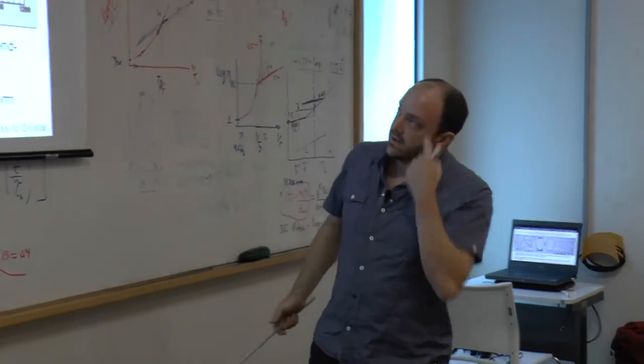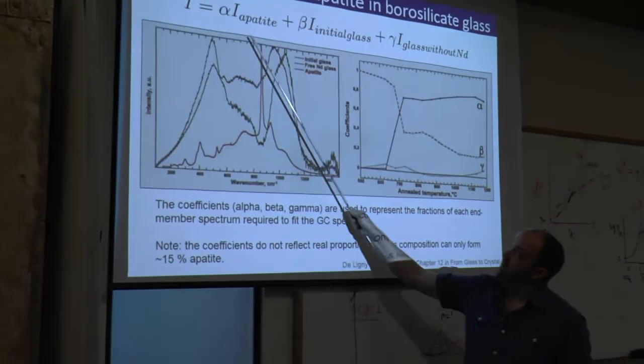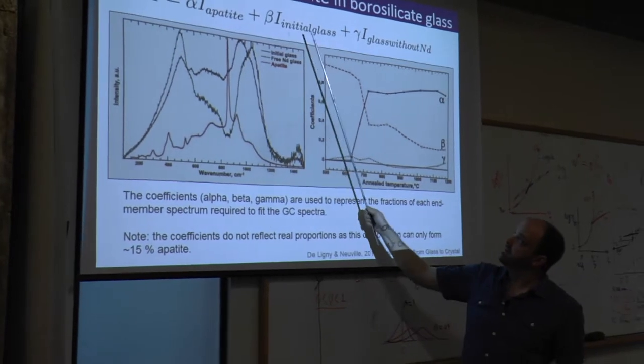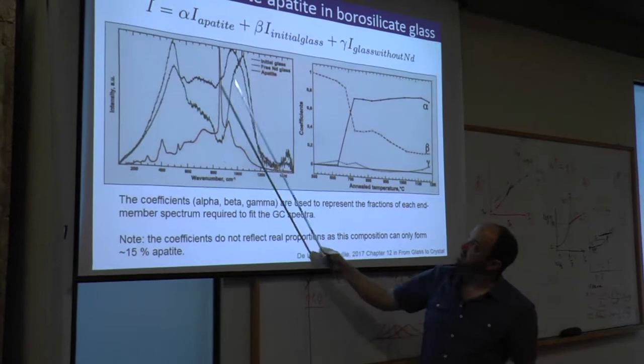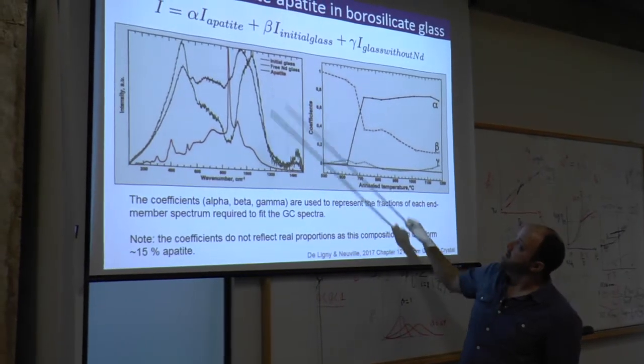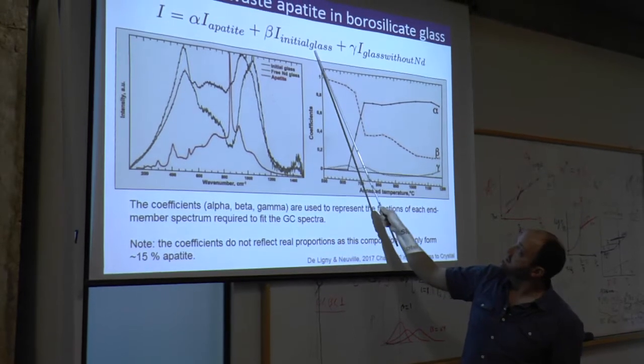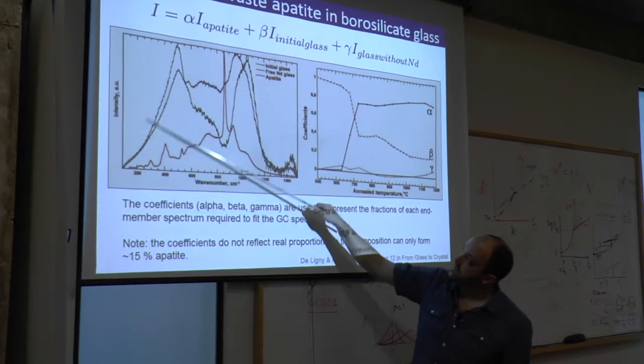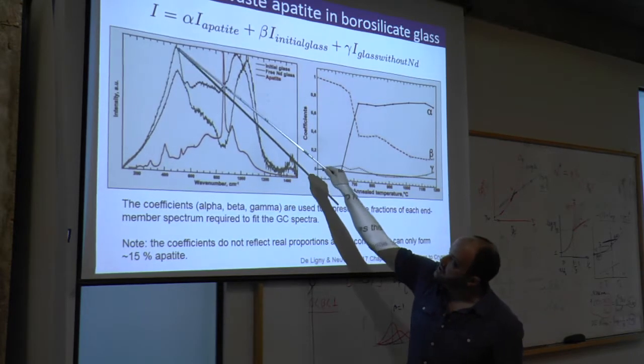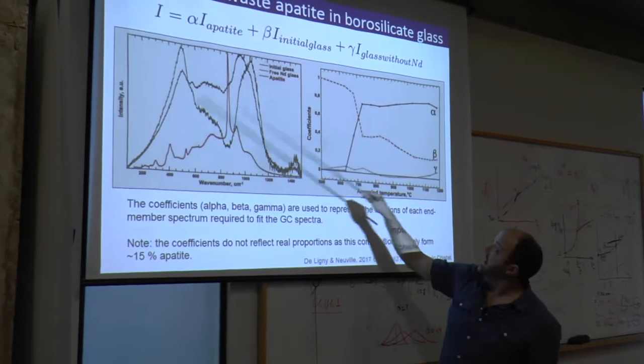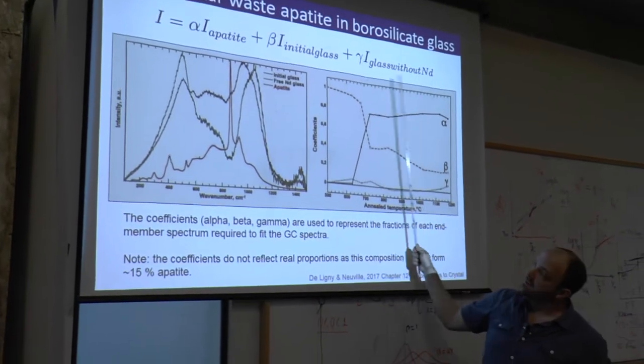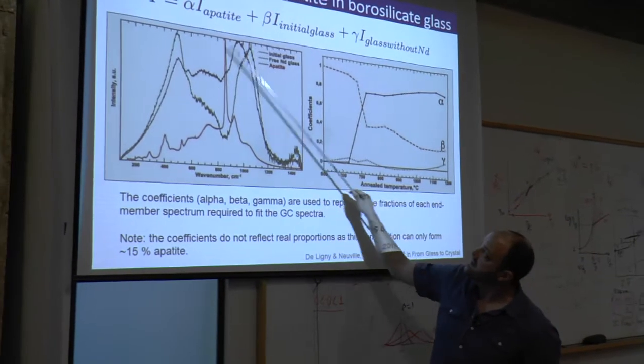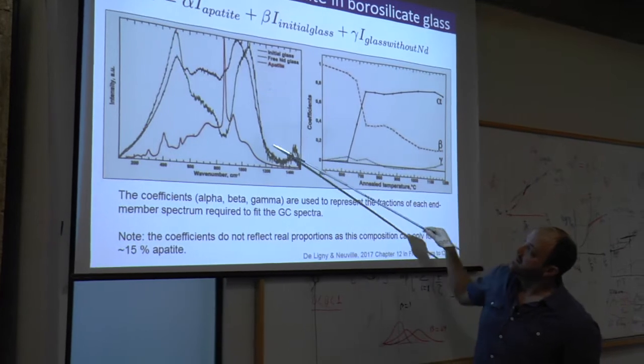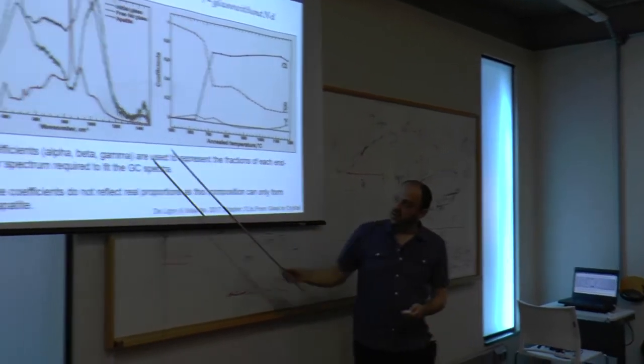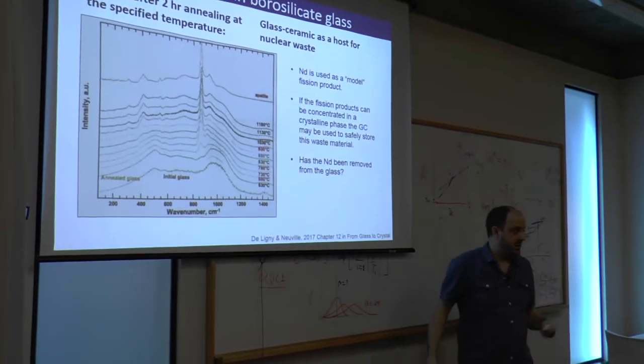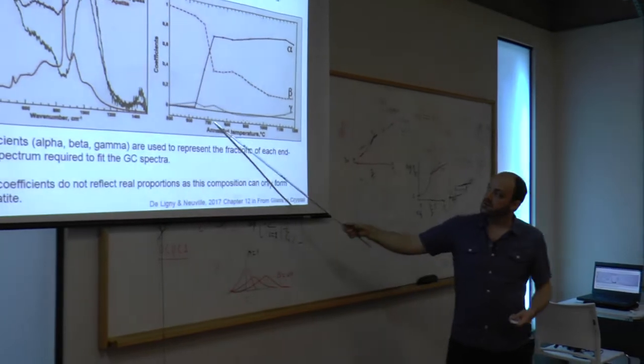So, how do we do that? What they did was use a linear combination of the spectra of the different materials. So here's the intensity spectrum of apatite. This is this red spectrum here. The intensity of the glass that has neodymium, this is one of their starting materials. So this is the initial glass with the neodymium in this blue. And the final is the glass without neodymium. This was their goal. And here is the neodymium-free glass that they looked at. So they did a linear combination of these three spectra and used it to fit all these different spectra annealed at the different temperatures. And what they showed is this.